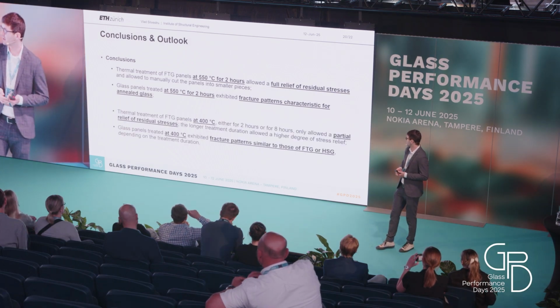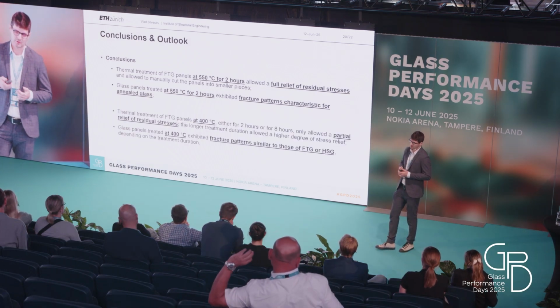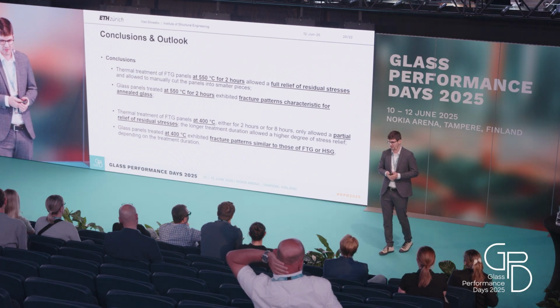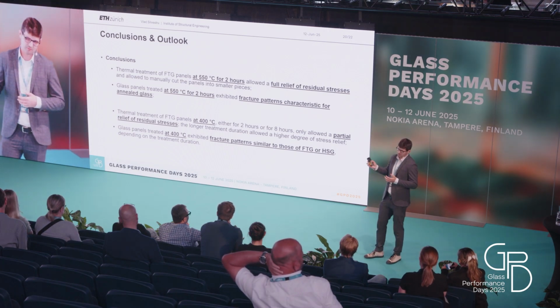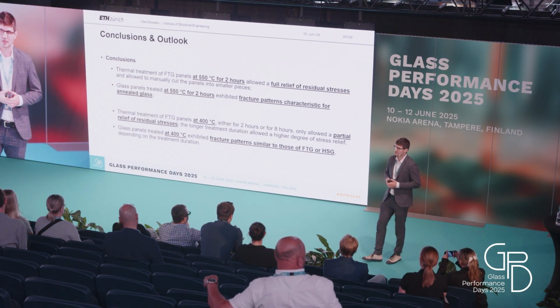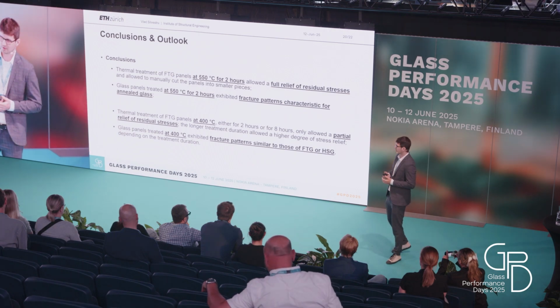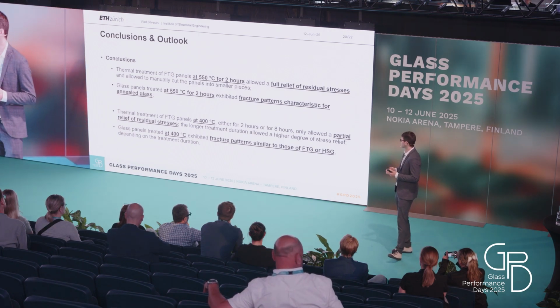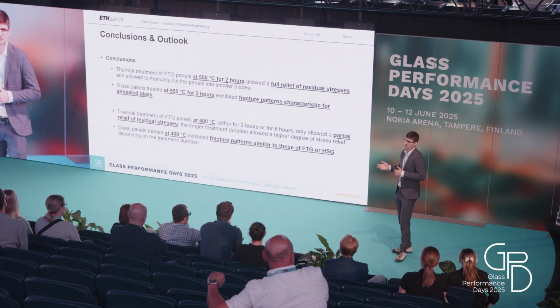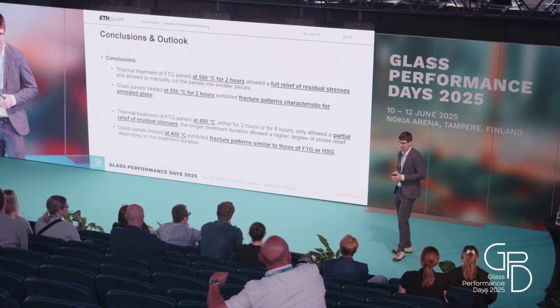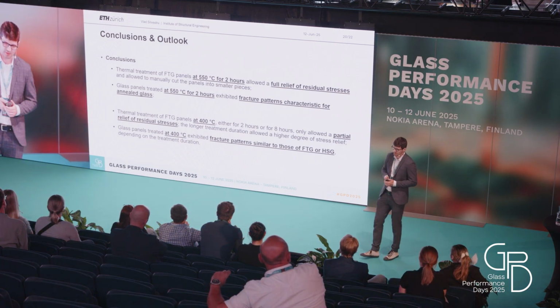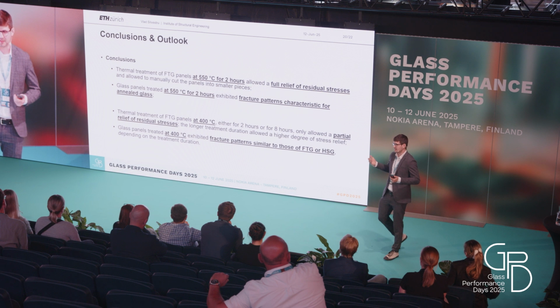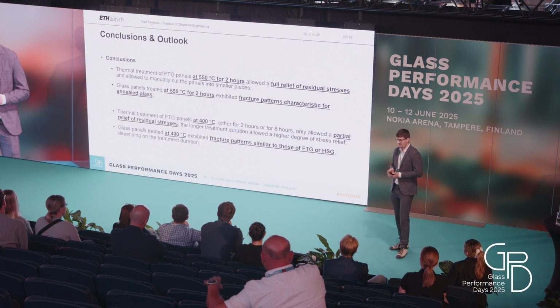Treating at 400 degrees allows only a partial relief of residual stresses. With the longer duration, the reduction is higher, of course, but the fracture patterns are still typical for tempered glass, depending on the duration, either fully tempered glass or heat-strengthened glass. So for this, I didn't even try to cut them because it doesn't make sense.